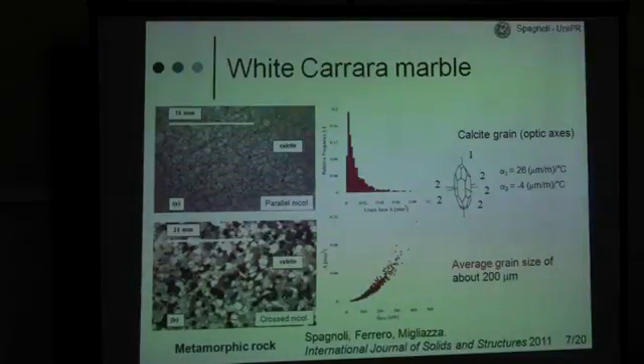As for the orientation of the grains, there is some important characteristic related to the thermal deformability of these grains of calcite, which is anisotropic, and this was investigated in some previous work of ours, where we built a model to describe this anisotropic thermal behavior, and to relate this behavior with the overall bowing of the marble slabs.